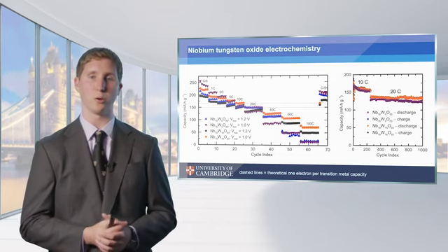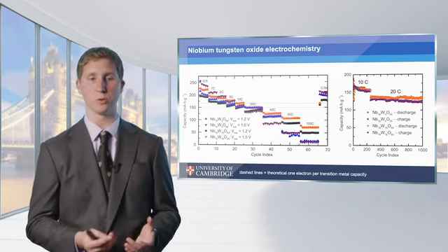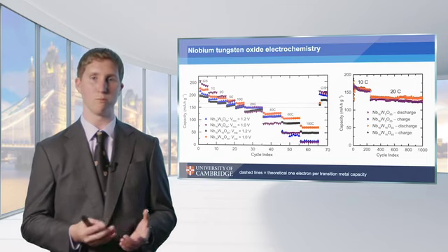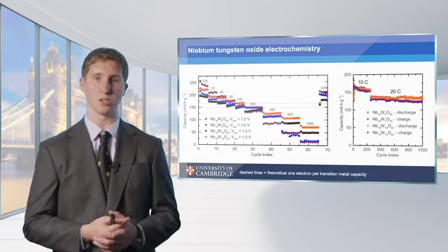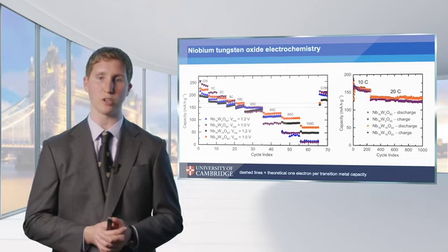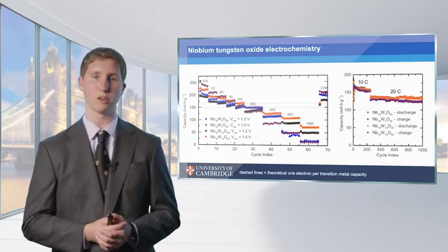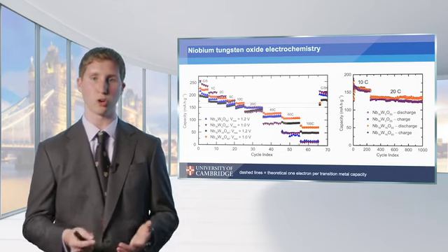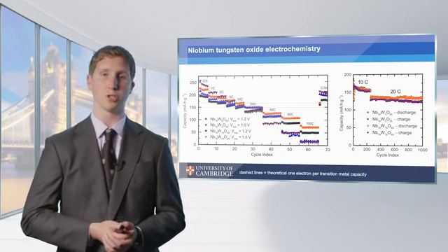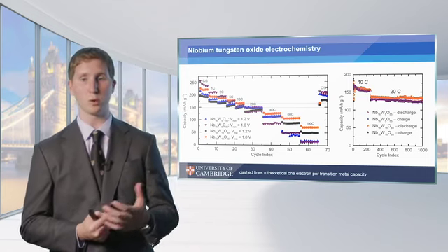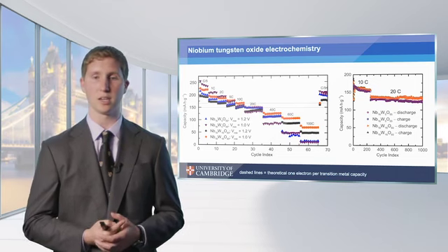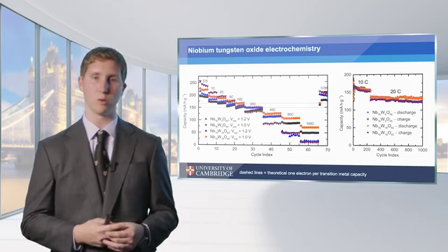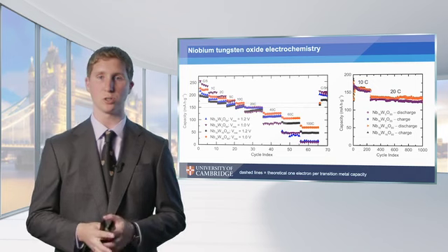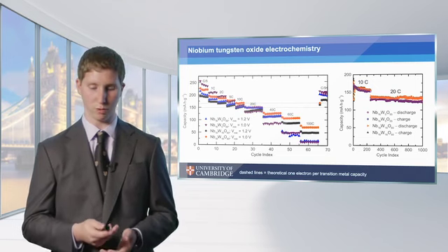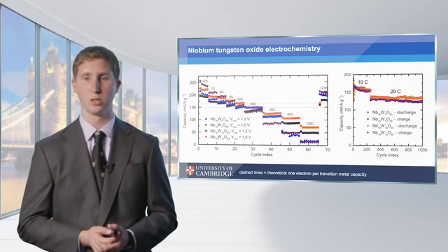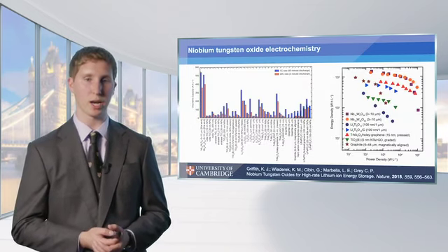They're able to do it without losing capacity. And so if you try and do even moderately fast charging, supercharging, things like that in your electric vehicle now, it does cause some degradation to the battery and will lead to a shorter expected cycle life. So you won't be able to discharge as many times. But with these advanced oxide anodes, we don't see any of that degradation. So not only should it be safer, but we should be able to do it for many thousands of cycles and get a much longer lifetime out of our batteries.